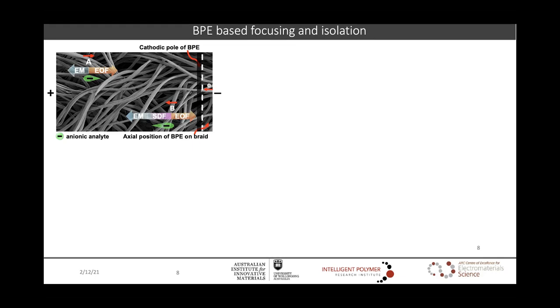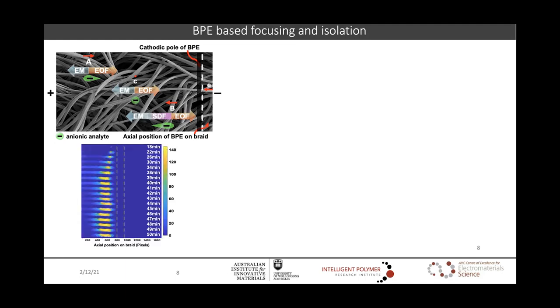The focused and concentrated ion can be isolated at one position when these two forces become equal in magnitude, which can be achieved by several methods, such as by manipulating the driving electric fields at the driving electrodes, or by introducing some siphon-driven force. Therefore, we demonstrated that with controlled conditions, you can see that anionic fluorescein remained focused at one point, even for 1 hour of running the electric field.